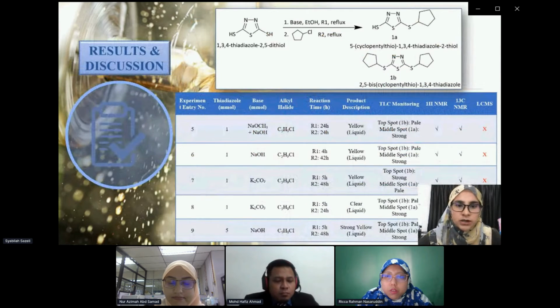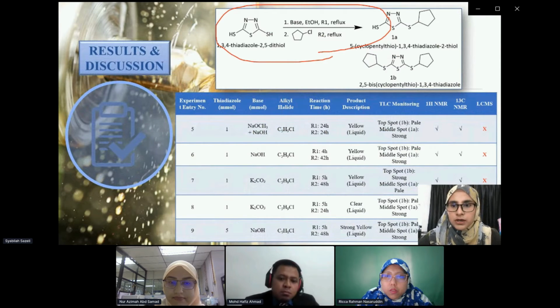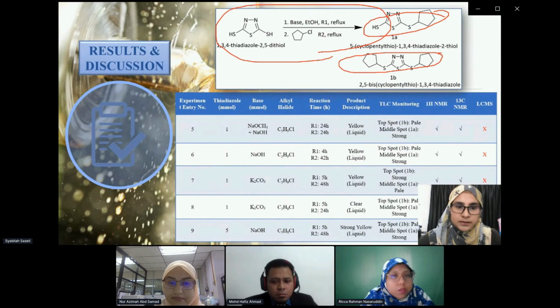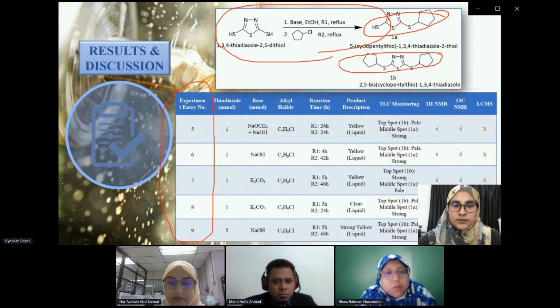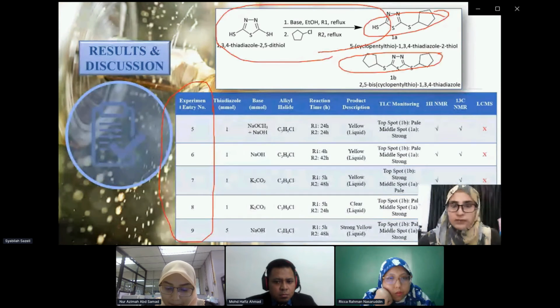So for result discussion, from this reaction, there are two compound structures produced, which are monoalkylated thiadiazole and bisalkylated thiadiazole. According to the experimental entries here, there are 5 reactions done for this experiment with different parameters. All the entries have different results after experimental workup. So we use different solvents to separate product and unreacted reactant and to determine the suitable eluent for column chromatography